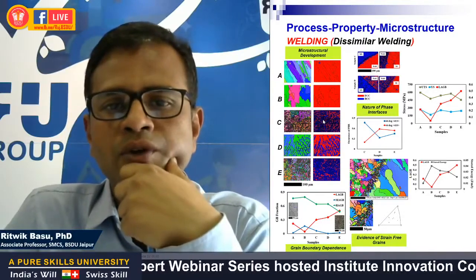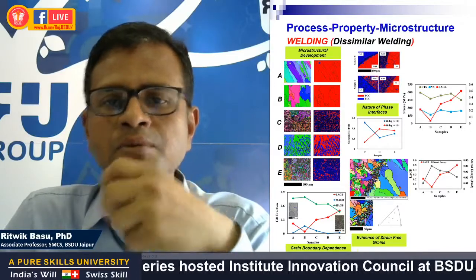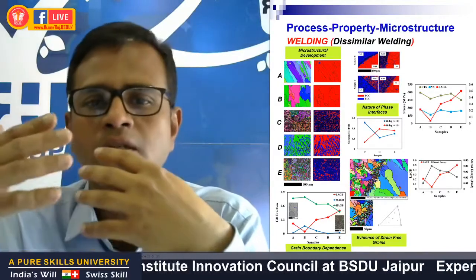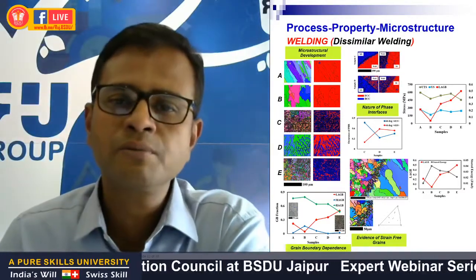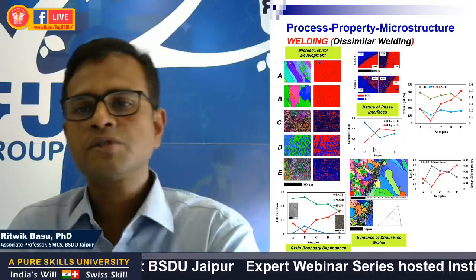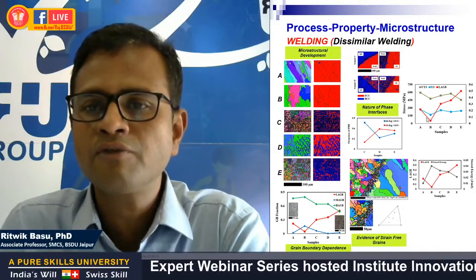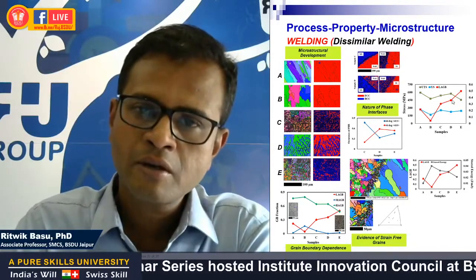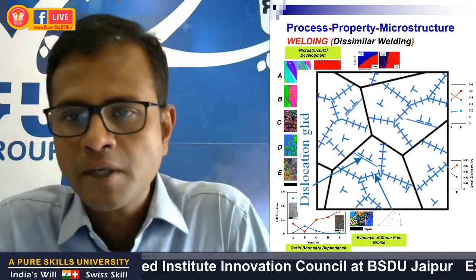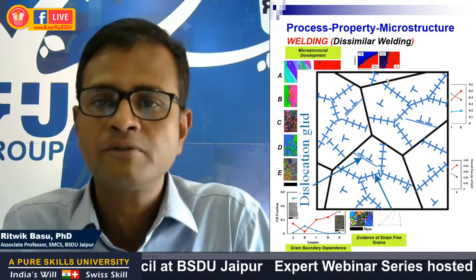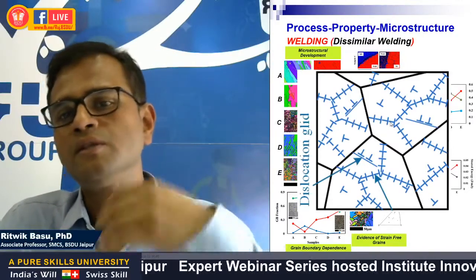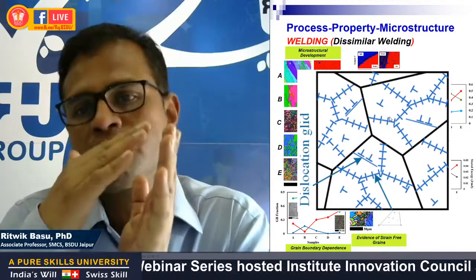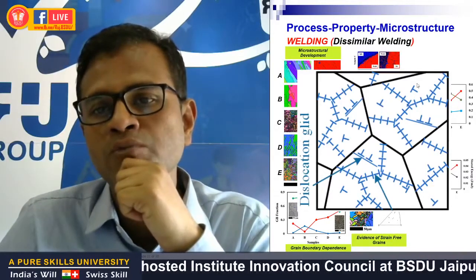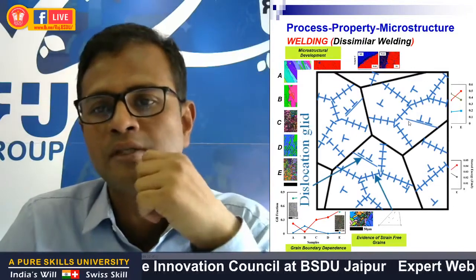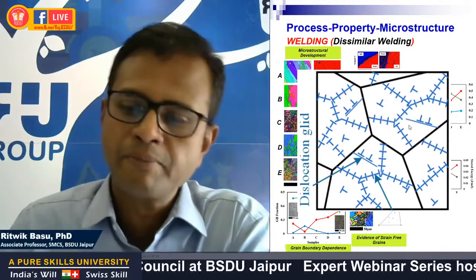We found that for samples exhibiting a two-phase microstructure, a particular orientation relationship between austenite and delta ferrite exists. However, their relative presence differed between the samples. So the strength of the welded joint was seen to be a clear function of the low-angle grain boundary fraction. So low-angle grain boundaries exhibit discrete dislocation arrays inside a grain, while high angle grain boundaries primarily remain at the actual grain boundaries of the material in the microstructure. So with an increase in the low angle grain boundaries, these dislocation walls are refined and finely spaced, therefore impeding the movement of other slip dislocations across the boundaries, leading to strengthening of the weld joint when stresses are applied.